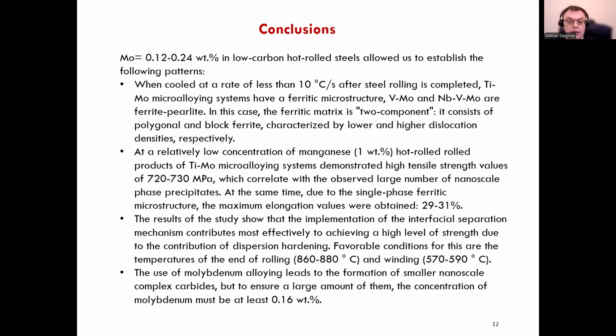In this case, the ferritic matrix is two-component. It consists of polygonal and block ferrite, characterized by low and high dislocation densities, respectively. At a relatively low concentration of manganese, on average 1%, hot rolled products of the titanium-molybdenum microalloying system demonstrated high tensile strength values of 730 megapascals, which correlate with the observed large number of nanoscale phase precipitates. At the same time, due to the single-phase ferritic microstructure, the maximum elongation values were obtained, up to 31%.